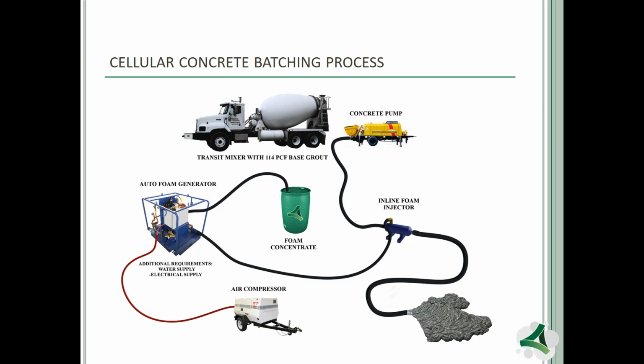The placement of cellular concrete in the most simplistic manner is where we take a neat cement mix or a cement water mix in a ready mix truck. We can put that through a pumper and then expand the concentrated foaming agent out through a foaming generator. And depending on the mixture and the recipe that we do, we'll then blend it together.